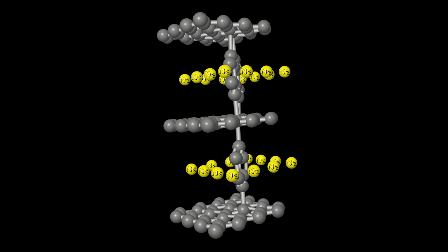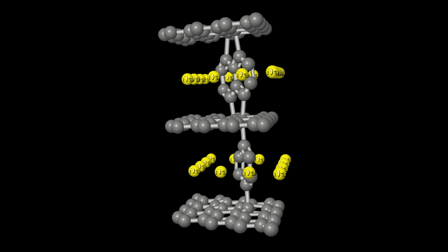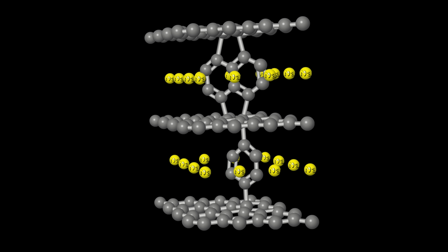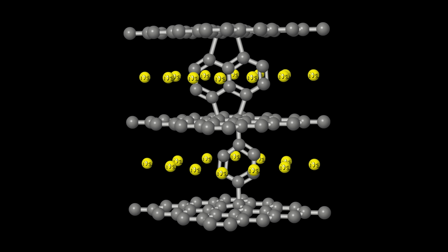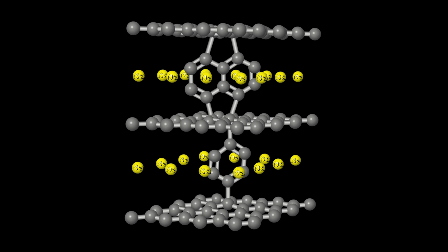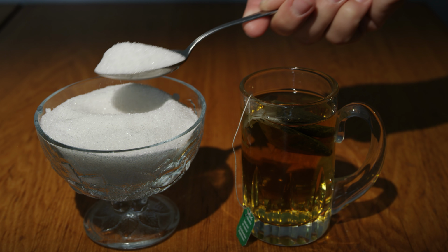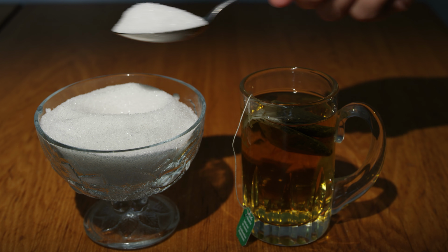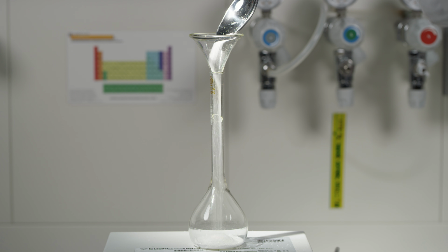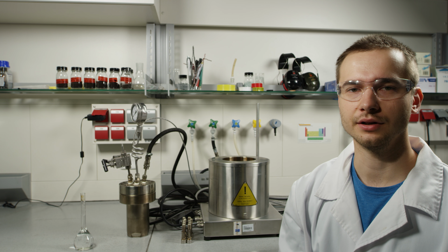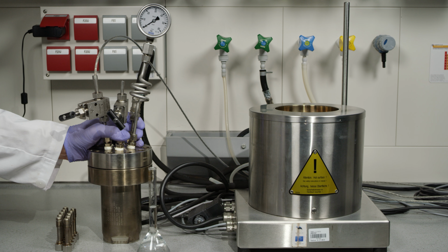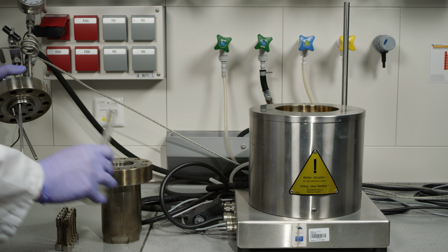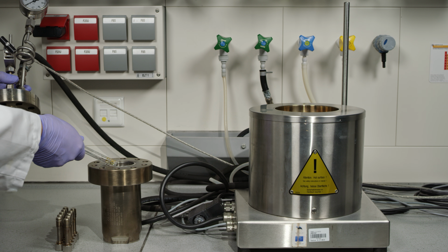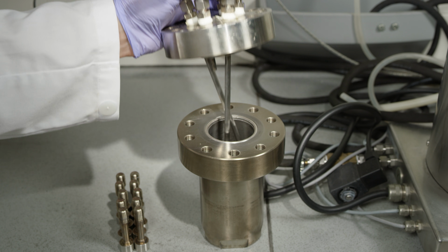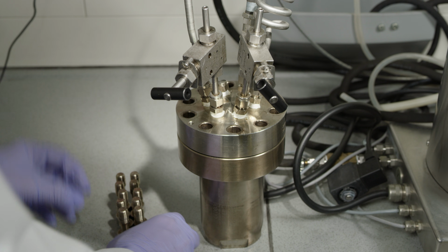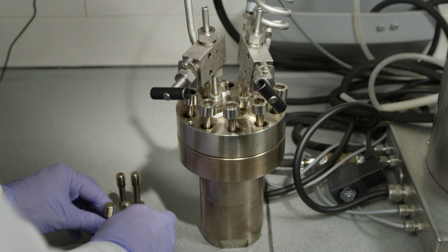However, we can't use graphite as a negative electrode in sodium-ion batteries because sodium does not intercalate into graphite as easily, so a different carbon is needed. Carbon for sodium-ion batteries can be obtained from different organic precursors, for example, sugar. This autoclave uses high pressures and temperatures to synthesize spherical carbon particles. Sugar solution is poured into the autoclave, which is then sealed and tightened firmly to withstand high pressures.